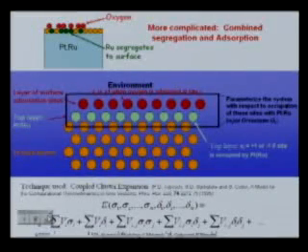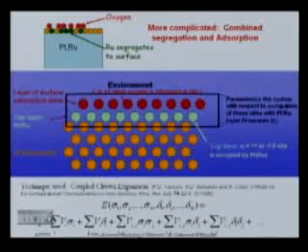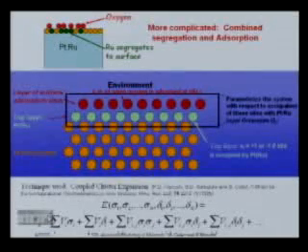Just to show you that you can push this a lot harder and make it a lot more complicated, I'll show you something a little more abstract, from a problem I worked on quite recently. It's adsorption-induced segregation, and here's the problem. The problem before was oxygen adsorbent on platinum. But if you have a platinum metal alloy, like a platinum metal catalyst, in this case platinum ruthenium, then you have two configurational problems. The first question is, what's on the surface? Is the site oxygen or vacancy?